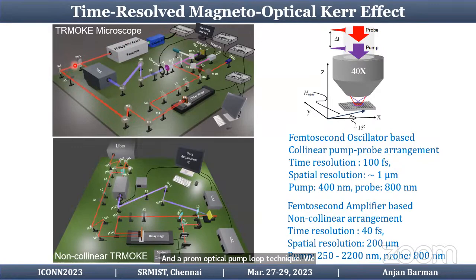We take a femtosecond laser and split it into two parts. The strong part goes through a second harmonic generator, so this is the red light, and it produces a blue light, and that is passed through a fixed time delay through various optics onto the sample, whereas the probe beam is passed through a variable delay generator, so that causes an optical delay between the pump and the probe beam, and then it is recombined with the pump beam and collinearly focused on the sample, so that we can actually measure the spatially and temporally resolved magnetization dynamics from the system with a spatial resolution of about 1 micrometer and a temporal resolution of 100 femtoseconds.